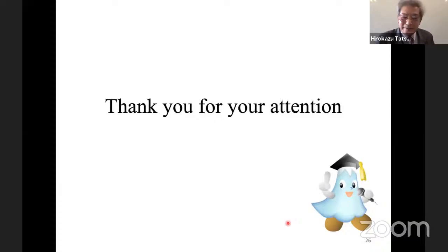Yes, oxidation is very, very important. I'm always struggling with oxidation. One thing is to do the reaction in a high vacuum, but that is still not enough. For structural characterizations, the oxidation does not affect the characteristics so much. But as a next step, we need to characterize electrical properties, and the oxidation affects these properties much more. So we need to avoid it. So now I'm trying to make this phenomenon occur in the liquid phase, to avoid oxidation.